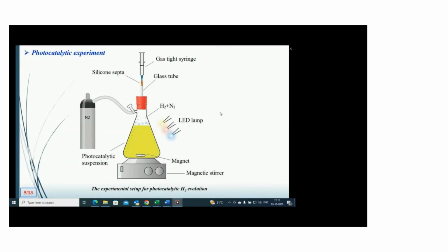In detail, 100 milligrams of photocatalyst powder was dispersed into 100 milliliters of aqueous solution of triethanolamine as sacrificial agent. Then, before the reaction, to eliminate the dissolved oxygen, the reactor was purged with nitrogen gas, and then the suspension was magnetically stirred and exposed to light irradiation for 4 hours. The gas samples were collected and injected into the gas chromatograph each hour, and then the amount of hydrogen was detected and quantified.